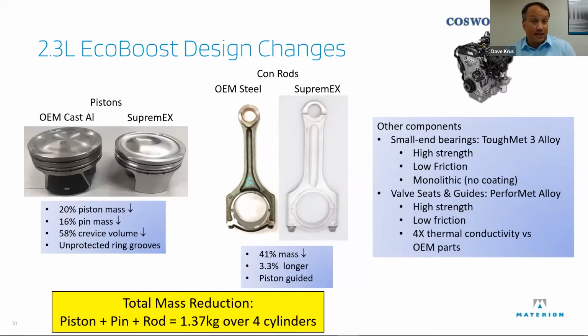Because you don't need that cast iron insert, and it's also stronger. The material is stronger at temperature, so you don't have to worry about it cracking, or the ring land cracking. They moved the crevice volume, or the crevice, up. They reduced the crevice volume by nearly 60%. And when fuel gets into the crevice, it doesn't burn. So that should be an efficiency gain.